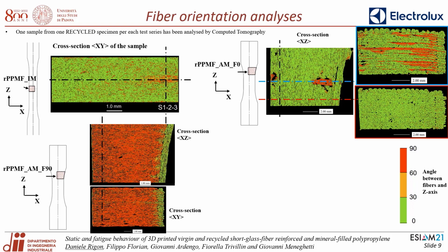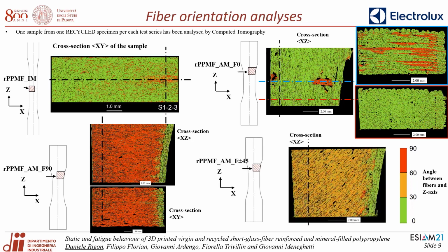The following analyses were carried out on the F90 specimens, where it can be clearly seen that the fibers are oriented at 90 degrees except, of course, in the wall part of the layer. And finally, the same features can be observed in the F45 specimen, where the fibers are oriented between 30 and 60 degrees.